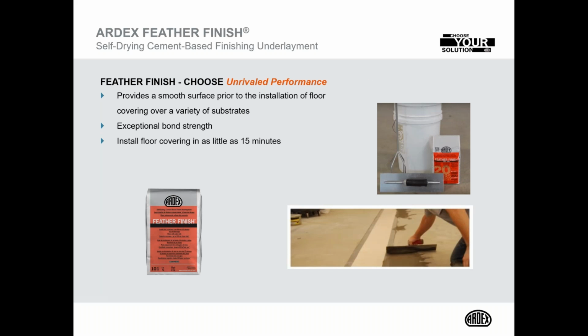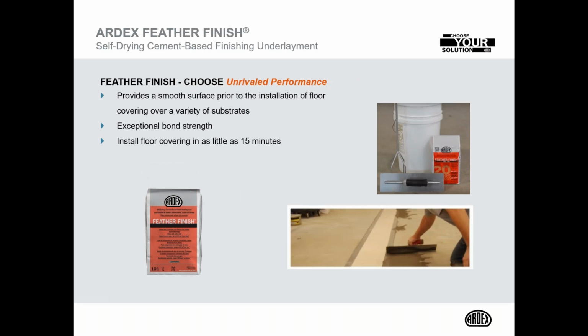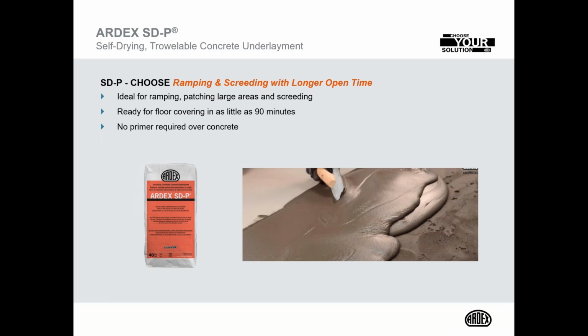Unsanded, mixes with water, sticks to virtually anything, self-drying. At a skim coat, I mean, it's done in like 15 minutes. 1/8 inch, 1/4 inch, you're hard enough for flooring in about 30 minutes to an hour. It's been the patch for a lot of years. Dating back to 93 is when we officially introduced that product. We also, back in the mid 90s, introduced a product called SDP. It's kind of called feather finish and SDP, like the 1-2 punch.